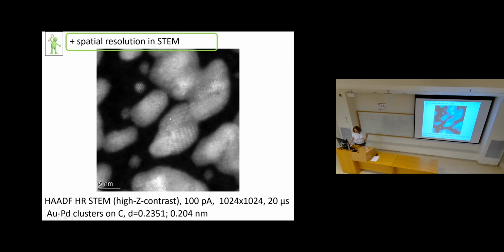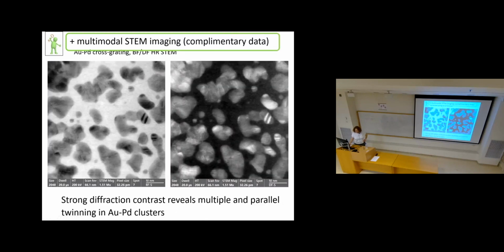So the contrast here is high Z contrast due to the heavy elements. And this is what we typically had in our previous configuration. Now we take this material, change the detectors, and acquire the image with a pair of bright field and dark field STEM detectors. Here is the bright field, here is the dark field, and what we have here is a lot of gray levels, and these gray levels tell us a story about the structural defects in this cluster.